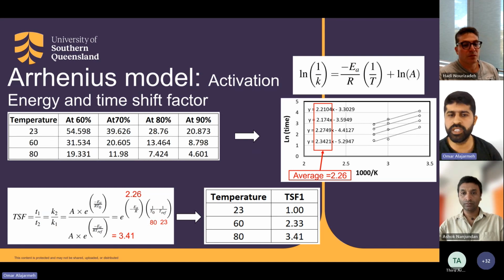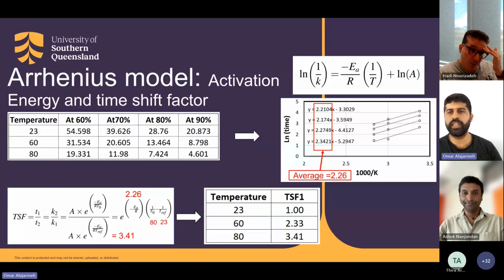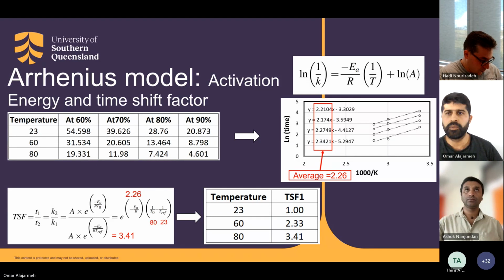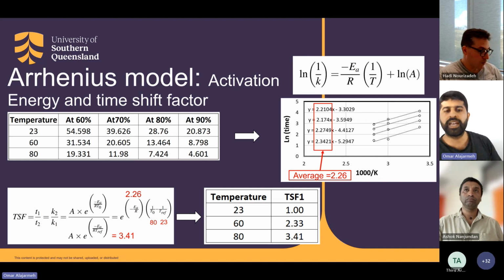Once we got the activation energy, we now look to get the shift factor. Shift factor means if your material is tested at room temperature, to degrade that material to a certain level, for example, for a polymer to reach 60% of the original strength at room temperature, you might need 1 year. But to accelerate that degradation, there is something called the time shift factor, TSF. You need to apply higher energy or higher temperature to accelerate that process. The TSF relationship requires the activation energy of the material, the reference temperature and the target temperature.